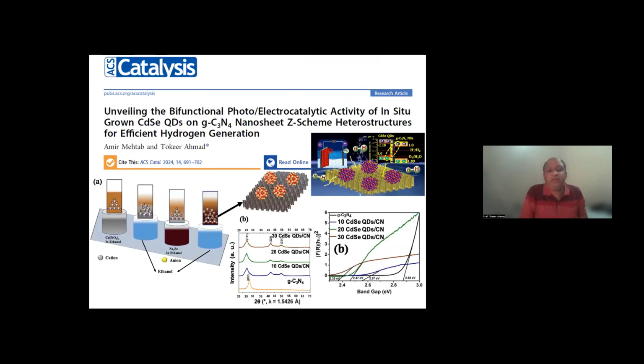Then we have designed and made the cadmium selenide. We have grown the cadmium selenide quantum dots over the graphitic carbon nitride sheets with the help of the SILAR cycles. And on the basis of the number of the SILAR cycles, we have classified these materials as 10, 20, or 30 in terms of the number of the SILAR cycles.